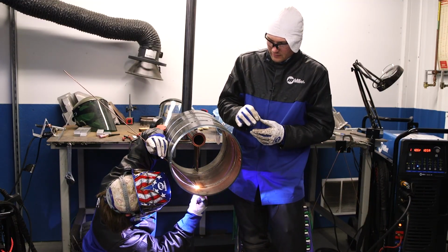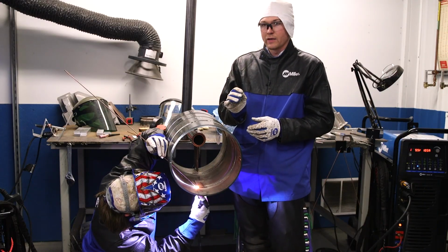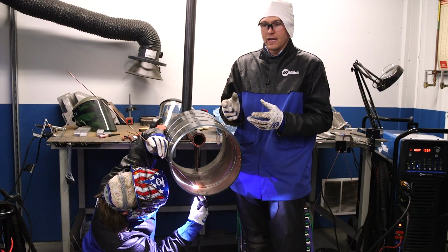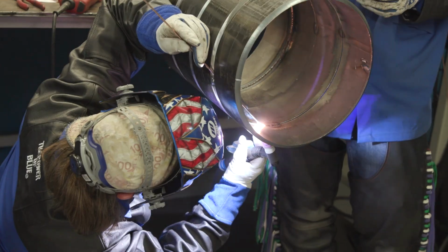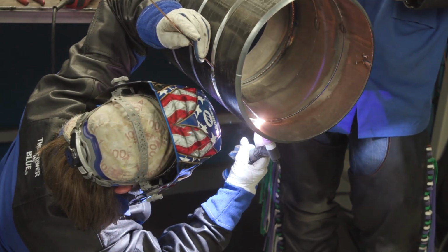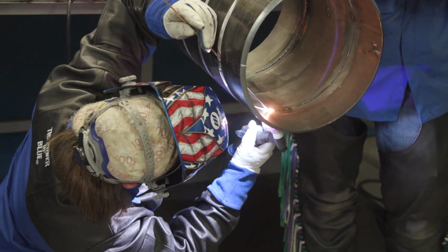Usually when guys get the rod stuck, it's because the internal leading edge of the weld puddle has still remained solid and not yet a liquid, but when you add into it, it will immediately turn into a liquid, and that's when you melt off from the side of the metal.